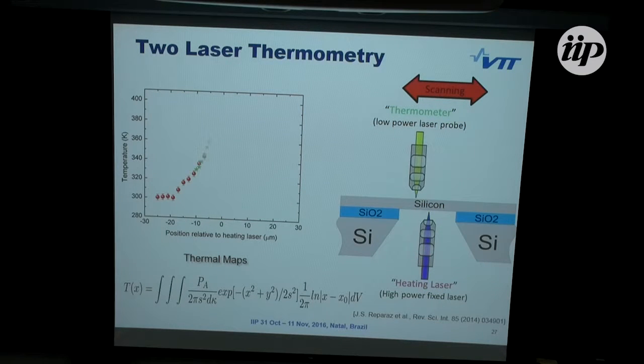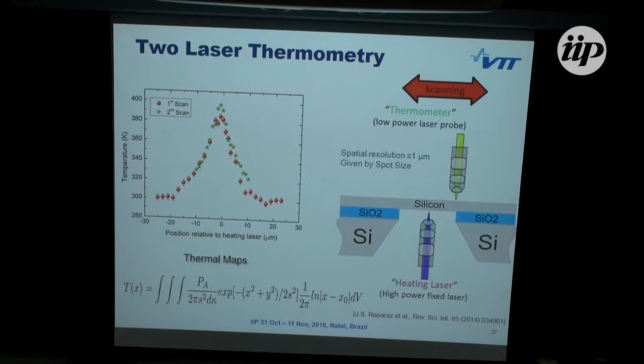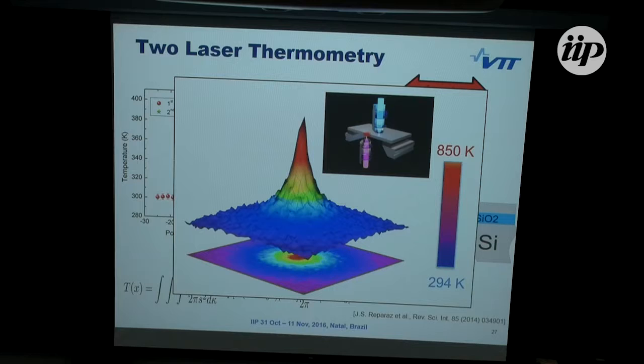A more sophisticated version of this measurement technique is so-called two-laser thermometry, where there's one stationary heating laser which hits, let's say, the center part of the membrane, and then there's another one with low power which measures the shift of the peak, meaning the temperature. So here we can have the true profile of the temperature, and then this can be modeled, and again the thermal conductivity is obtained from the slope, or the logarithm of the slope. And this has rather good spatial resolution, and with this technique you can get quite nice maps of the temperature.